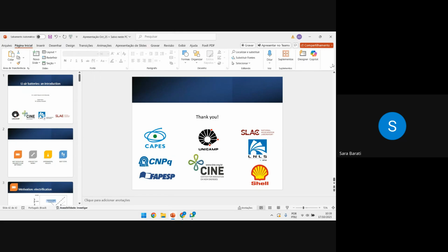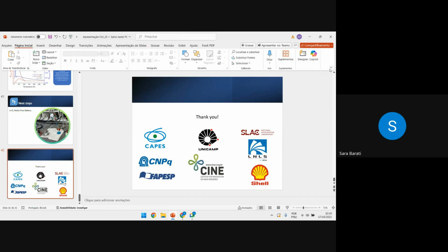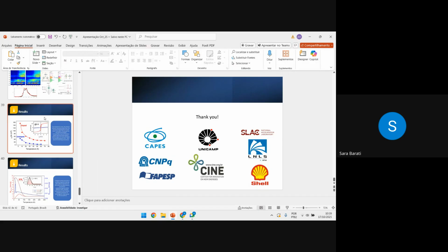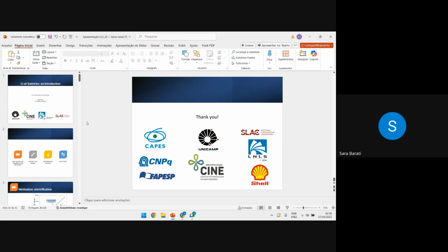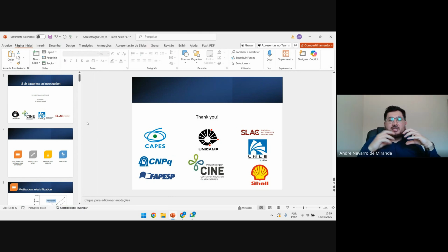Hi, Andre. Thank you for your nice presentation. I like it. My question is about the capacity fade. You talked about the most problem of this battery being capacity fade. What is the main reason or mechanism? Actually, it's the other way around. The catalytic defect is very good for the battery. When we say defect, it means you have some oxygen vacancies or some cationic vacancies that form a really high energy surface. And we like high energy surfaces because they are really good active sites for the formation and the decomposition of the lithium peroxide. So it's not a big problem. On the contrary, it's a solution for good catalysts.